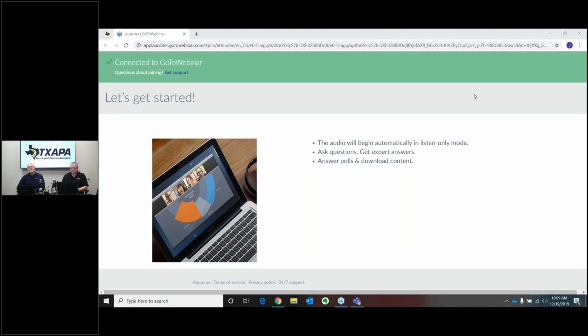And where this is different than previous specifications is instead of varying the criteria that you're measuring for, like you do for other petroleum products, let's say setting a standard temperature and then changing the criteria, you establish a criteria and then you change the temperatures at which you test it so that you're able to meet those requirements over a range of temperatures that relates to what you're using them for in the actual pavement. And so with this, when you see these numbers, those are actually temperatures in degrees Celsius, and they represent a range of temperatures that under normal conditions you would expect an asphalt binder to perform suitably to resist rutting and cracking.